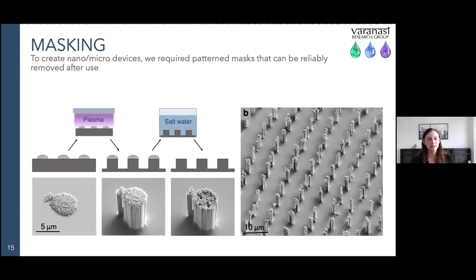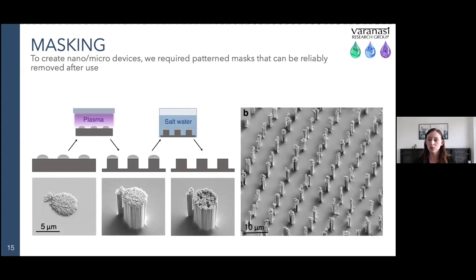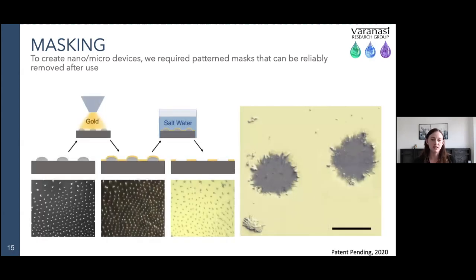In addition to being interesting, this is also functional. We now have a water-soluble mask patterned on a micro or nanoscale length scale. I took one of these periodic array patterns, put it in a reactive ion etch which created a three-dimensional structure, then put it into salt water which dissolved the crystals, leaving a periodic three-dimensional micro-scale textured surface — something you normally can only form using complicated steps involving adding and removing a mask. You can also do this with sputtering to create a two-dimensional patterned surface chemistry.